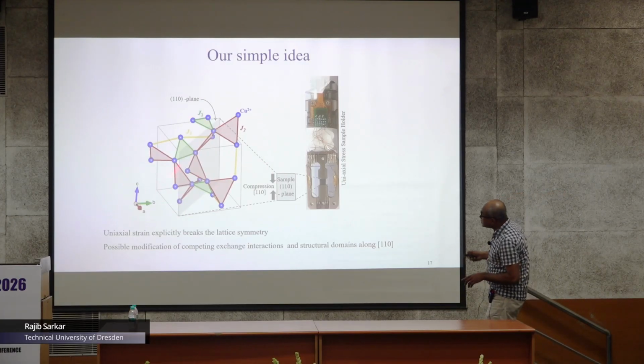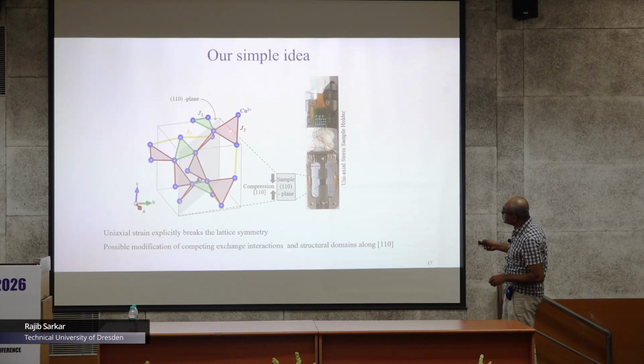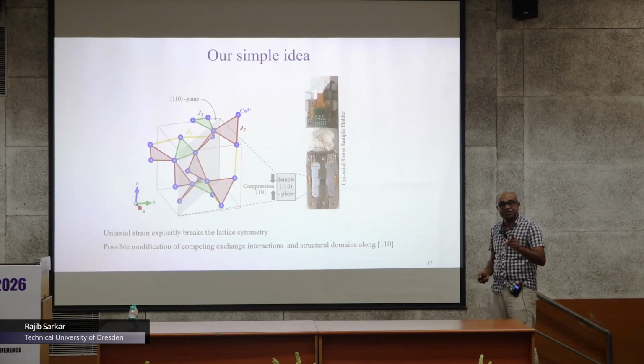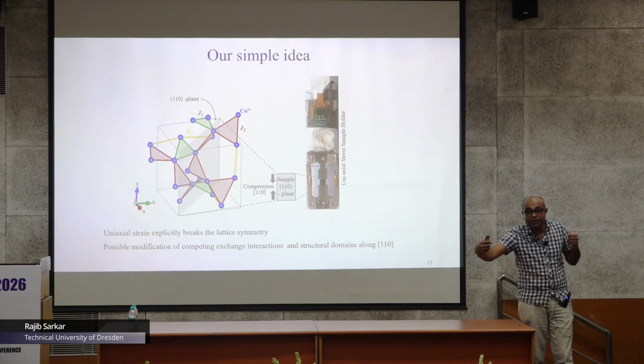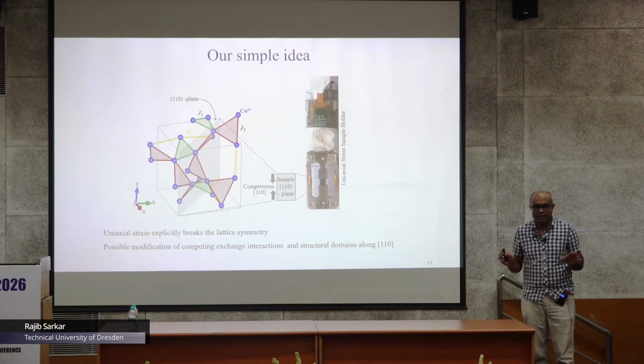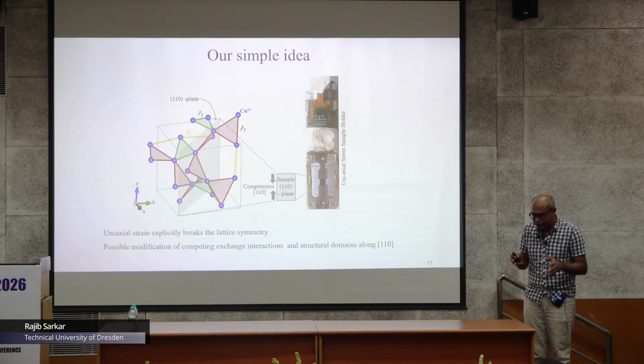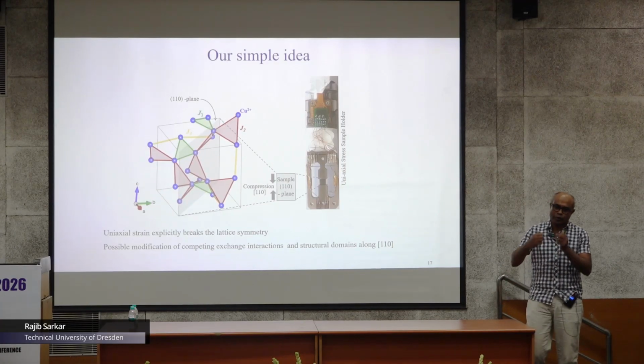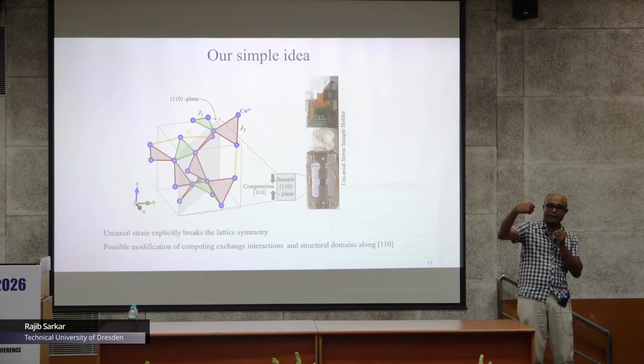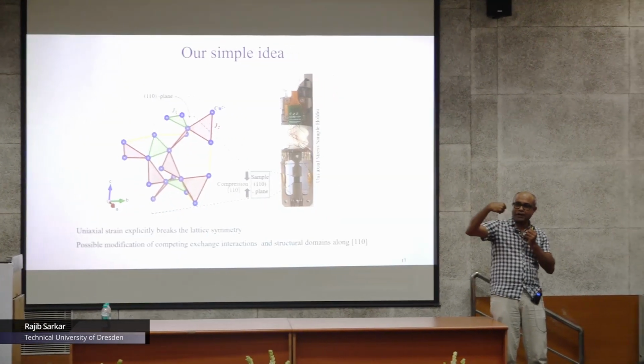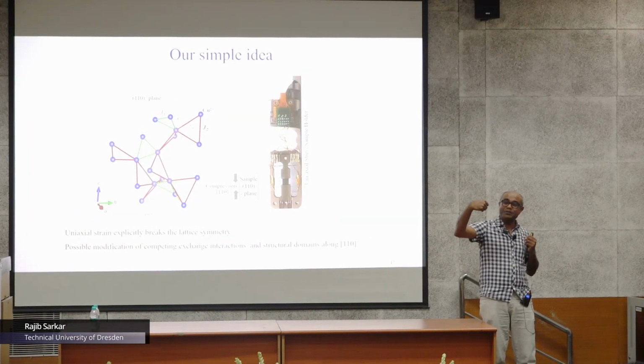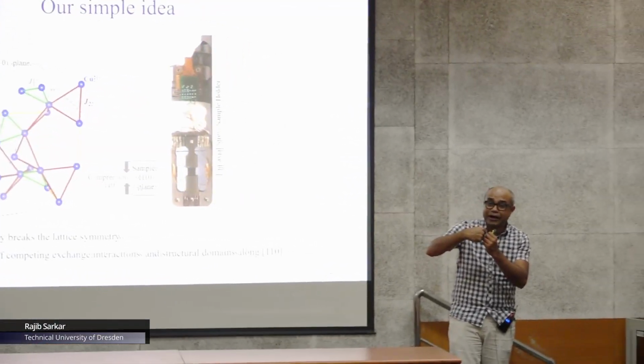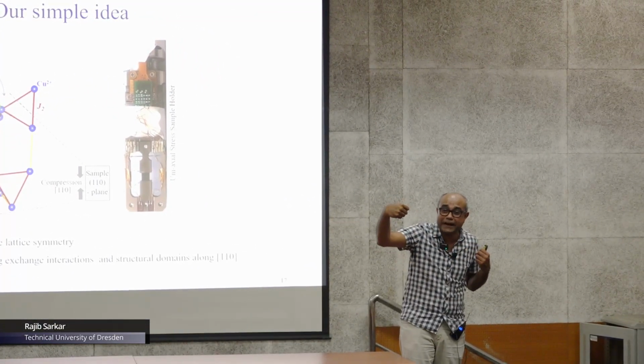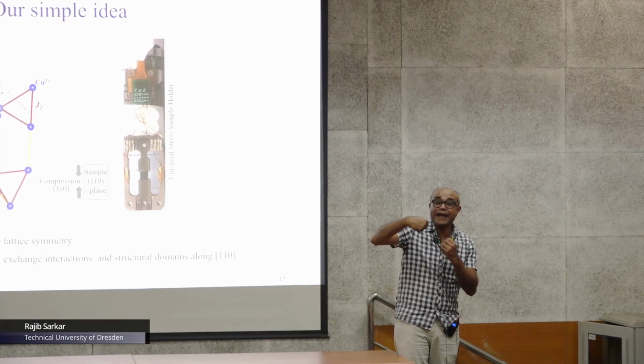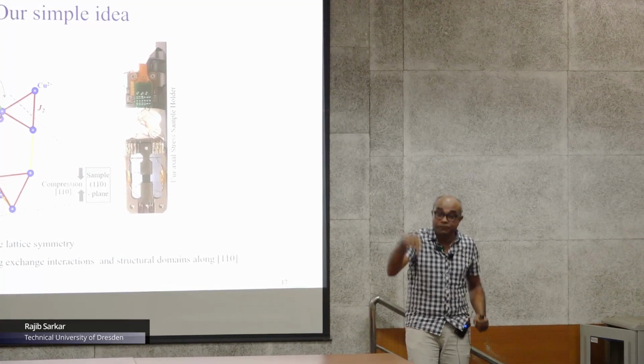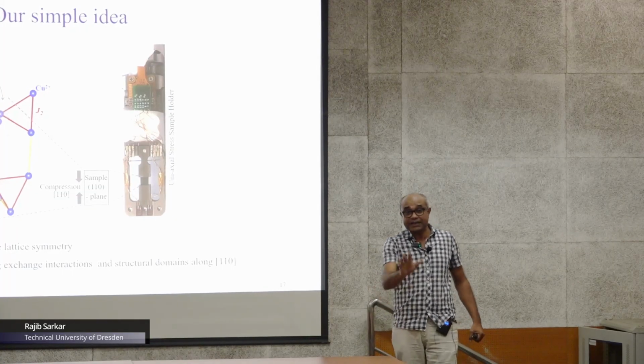So how did we do it? You see, this is the hyper-Kagome structure, and this 110 plane is the interesting plane in which to apply the uniaxial strain. The idea is very simple, but to make it work is very complicated. What we wanted to do: I have a 110 plane, and now I want to make a strain along this 110 direction. So what will happen then? You will change all the exchange energies, because you are changing the lattice parameters, right? That means you try to break some kind of symmetry, and that will influence all the properties you are going to measure. That's the simple idea.